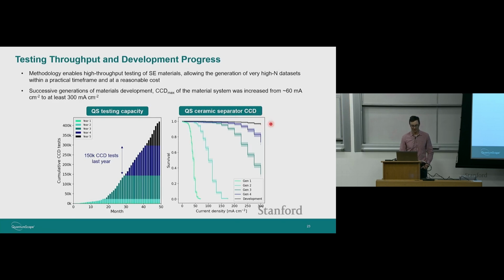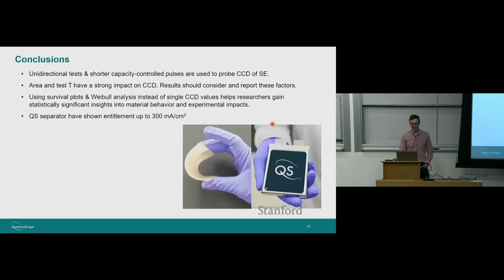So this curve on the right is not the latest and greatest, but a relatively recent population where you can see over 90% survival at 300 milliamps per square centimeter. So a pretty impressive result. This is what we use then to gain confidence that our batteries should work in the field. They've got some considerable factor of safety. So I'm right here at the end and right at about time.